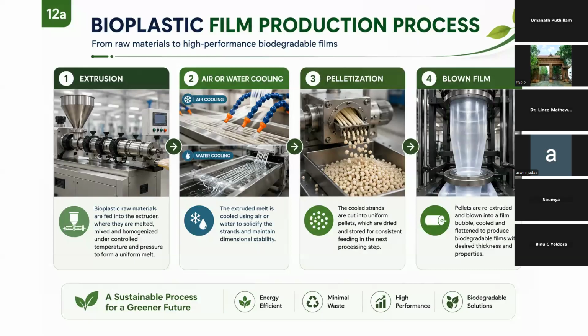If we use any bio pigments for giving some colors to the film, we can't use water cooling. So depending on the application, we have to choose air cooling or water cooling. And at this stage, the strands are then moved to the pelletizer, where they are cut into several small particles. Those pellets are introduced to the blown film process to melt again and blow into the desired shape.